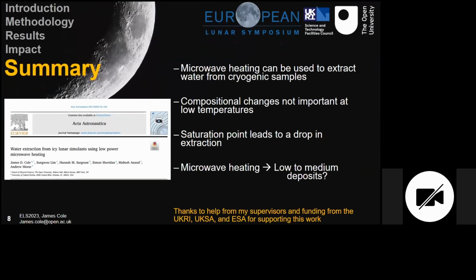Okay. Just in summary, we found that microwave heating can be used to extract water from cryogenic samples. We've done it at a lower power threshold than has been done before. We found that compositional changes are not that important at lower temperatures for microwave heating, and that at the saturation point, this leads to quite a significant drop in the extraction. So for these points where we think there might be 38% water, this effect could be even more pronounced and might be more of an issue. So microwave heating overall might be better suited for low to medium ice deposits.